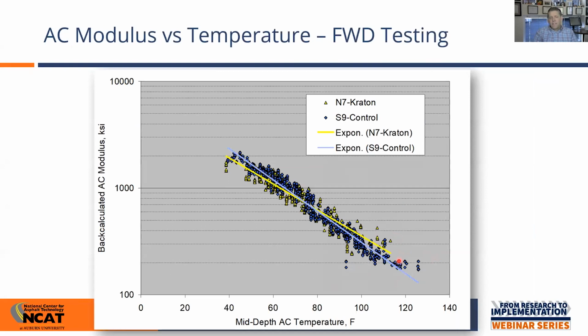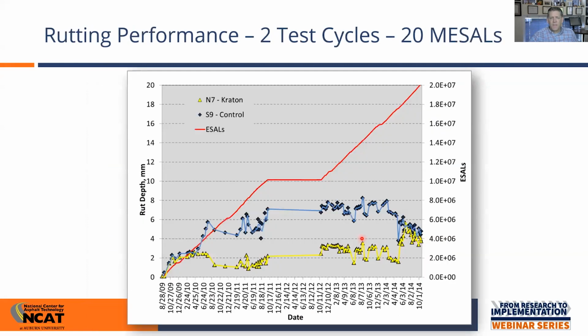We do a lot of FWD testing and back calculation at the track, and that's what this plot is showing over the several years worth of testing. And it's interesting that we got very similar modulus, especially right around, say, about 75 degrees or so, where these two lines cross. The yellow is Kraton, the blue is the control. But we see that it's a bit softer at the low temperature and a bit higher at the high temperature. And we see this from conventional polymer loading as well. But we see kind of a shallower slope, and we're seeing some advantages here that come out in the rutting and cracking performance in the modulus curve. So comparable, but a different slope that we get from the data.